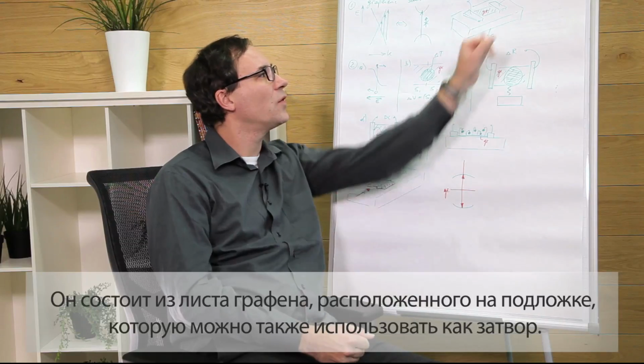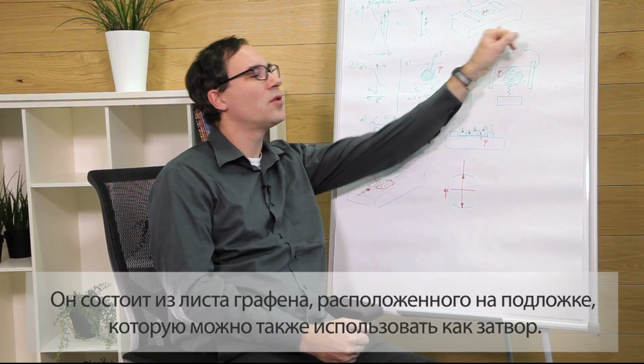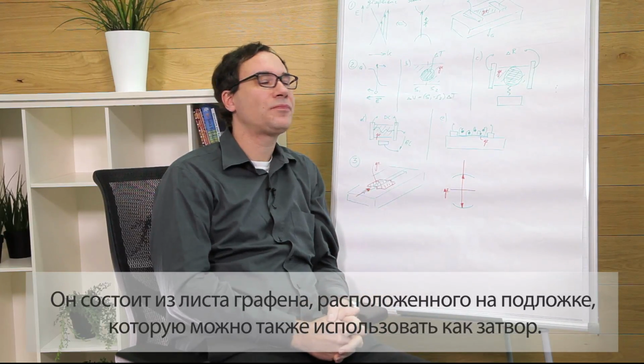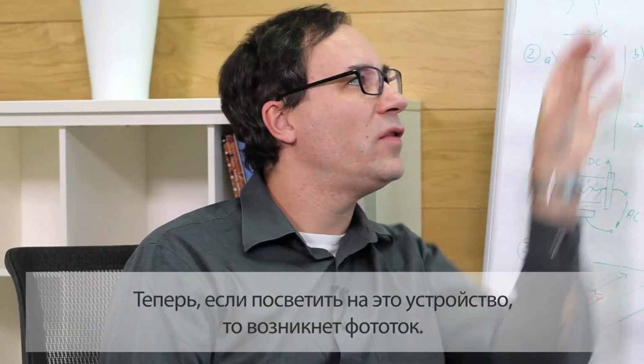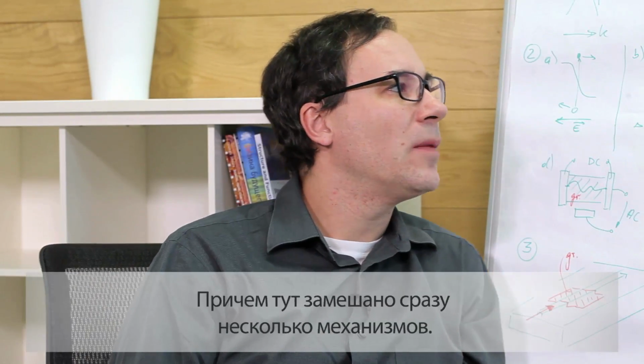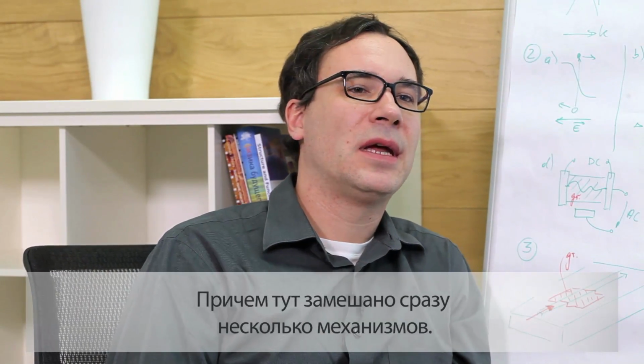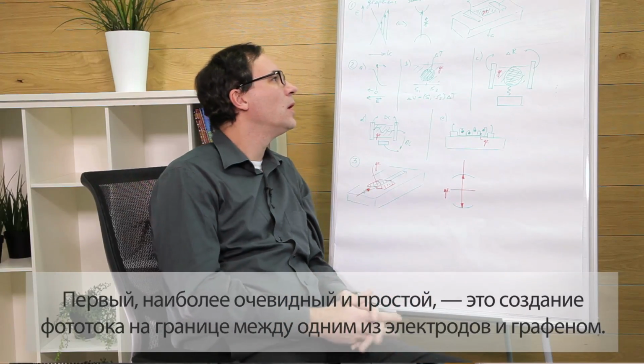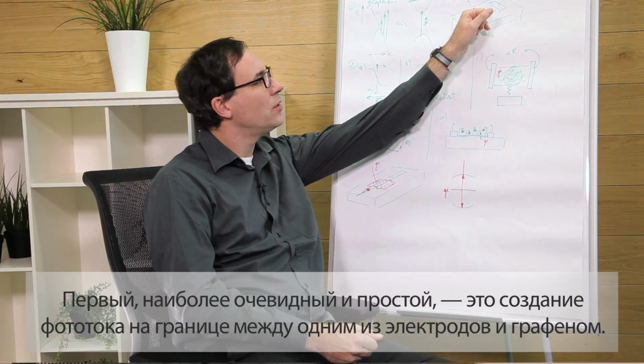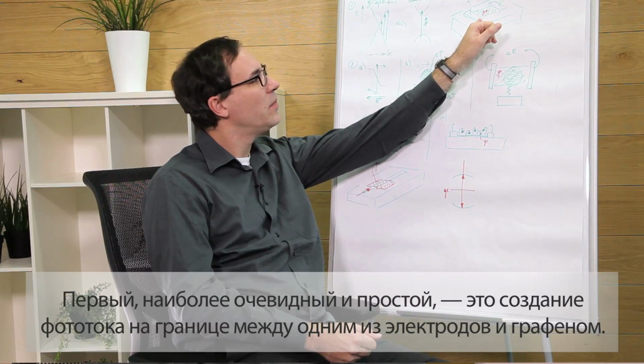Now, the simplest device that we used in the beginning is shown here. It's just a standard graphene thin film transistor, where we have a graphene sheet that we put on some substrate that we can also use as a gate electrode. And we put drain and source electrodes on both sides. Now if we shine light onto this device, we saw that there are different mechanisms that contribute to the photocurrent. The first one, and the most obvious and easiest mechanism, is that you generate a photocurrent at the interface between one of those electrodes and the graphene sheet.